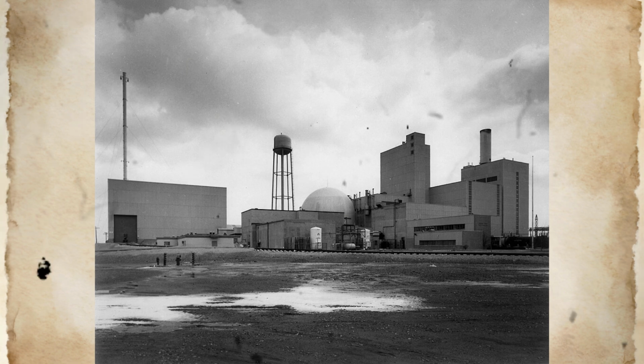The zircaloy cladding had experienced rapid oxidation above critical temperature thresholds, creating oxide layers that reduced effective wall thickness and degraded mechanical properties. Thermal stress from temperature gradients and differential thermal expansion had created mechanical loading that exceeded ultimate strength limits of the oxidized cladding material.